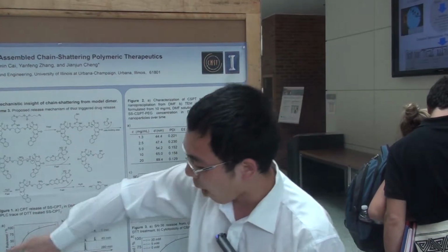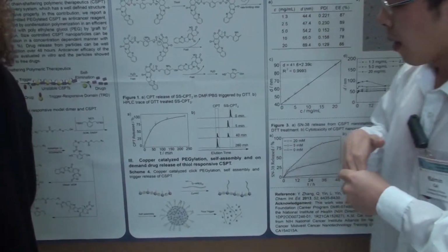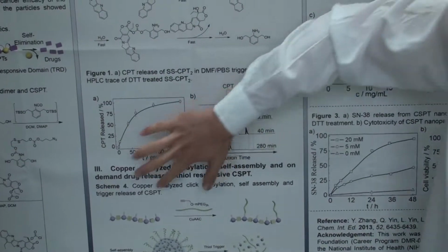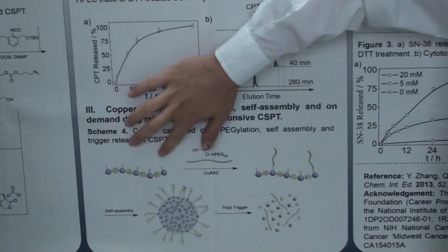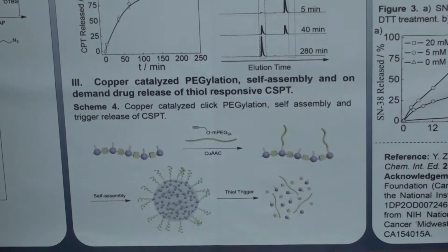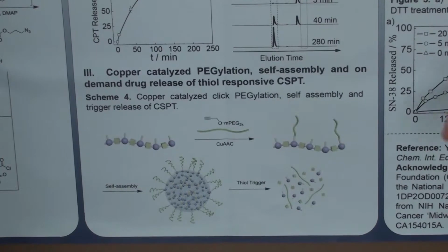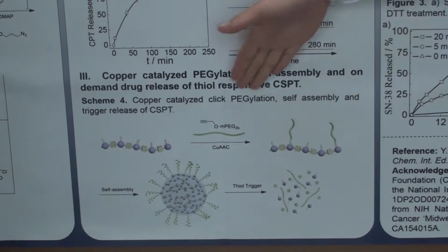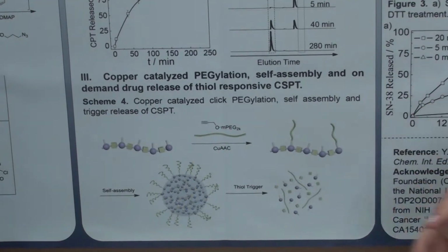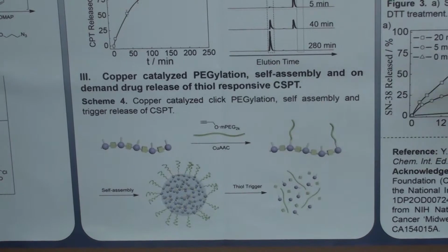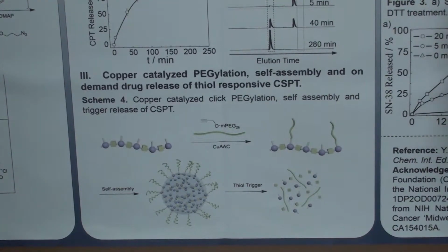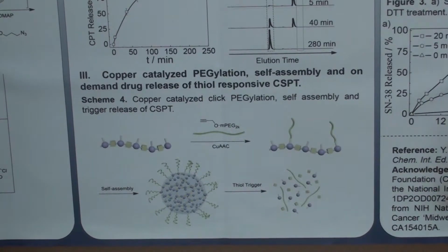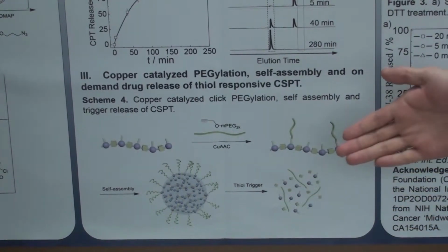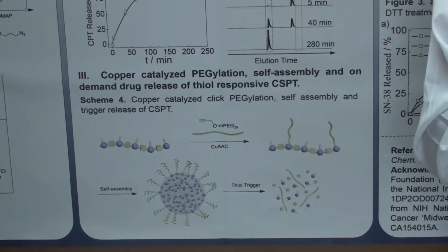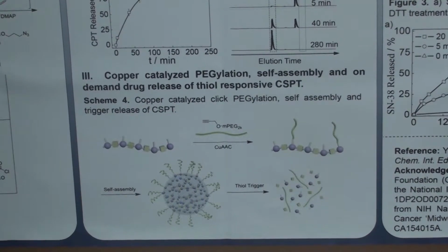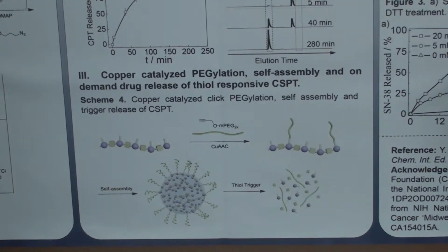So here is basically the structure of my polymers. We have designed polymer chains which have the drug as the backbone of the polymers, and the polymer chain is hydrophobic. Through a certain chemistry we can modify the drug polymer itself with amphiphilic polyethylene glycol, which makes this polymer drug itself amphiphilic. And very interestingly, the polymer itself can self-assemble into very stable nanoparticles, which only release the drugs in the presence of the certain trigger we designed. In this case, it is a cell trigger, which has a very high concentration in the intracellular environment instead of the extracellular environment. This will make sure that our drugs will only release in the cancer cells instead of the blood circulation.